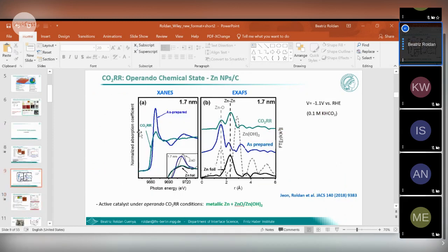We also want to know what happens to our catalyst under reaction conditions. So we started with a zinc catalyst and it was oxidized. And if you go to the synchrotron and you look, for example, with X-ray absorption spectroscopy, in this case, X-ray absorption near edge structure spectroscopy, you can follow how the as-prepared sample looks like. And you see clearly that the sample is oxidized. These are about 2 nanometer particles. And then under reaction conditions, you see significant reduction.